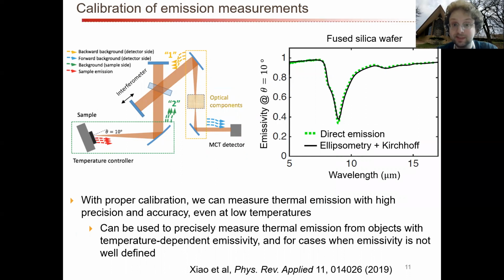Just to give you an example, here is the emissivity at an angle of 10 degrees. This is unpolarized or mixed polarization as a function of wavelength for a fused silica wafer, which is kind of a common reference we like to use. And this is at rather low temperatures. I think this is at something like 40 degrees. I don't remember the exact value.